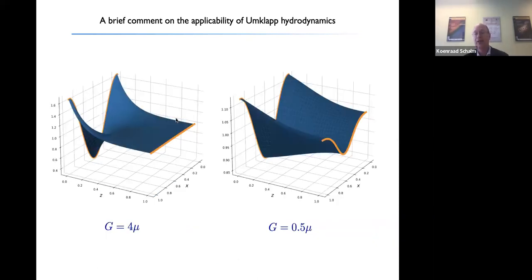Now, I mentioned one thing, that we could apply hydrodynamics in this system because the lattice momentum was small. And this is something that I want to emphasize. Again, remember, we are computing these black holes with an undulating horizon. And it is really important for this undulating, or modulated, horizon, or the fact that the lattice persists all the way down to the lowest temperatures, that your lattice vector is small in units of the hydrodynamic cutoff scale. And that's for a very simple reason that we all know: in quantum field theory, the lattice is a UV effect that just renormalizes away very, very rapidly. And if you take a very large lattice vector, G very large in terms of the hydrodynamic scale, that's exactly what happens.